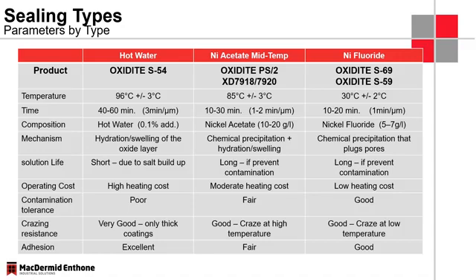One of the downsides for the cold seal is really that it interferes with some of the organic dyes. So generally speaking, when we talk organic dyes, a lot of people will still use the nickel acetate seals. They're more stable. They don't attack the dyes. It will not change the color shade significantly, and therefore it's really the process of choice when it comes to organic dyes.